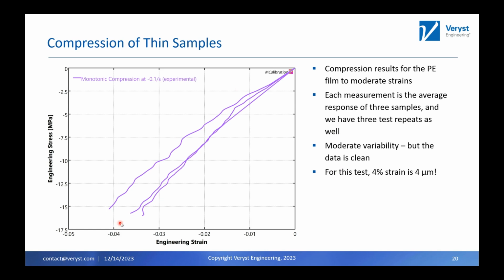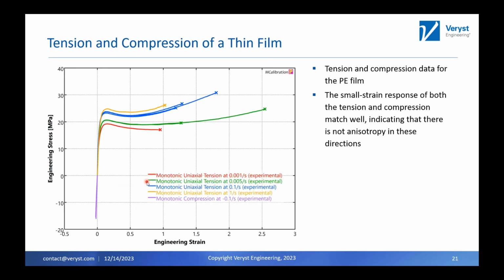The other thing to keep in mind is that 4% strain is 4 microns of displacement. So we've only compressed this thing to 4 microns of displacement. We're about 15 MPa. So there's a little bit of variability between these 3 samples, but given hopefully what your expectations are for testing something 100 microns thick in the through thickness, that's a pretty low variability there.